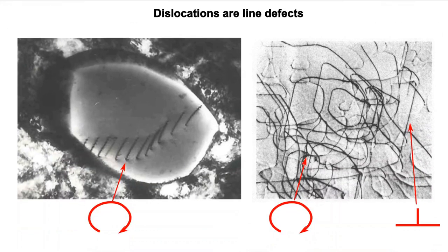These dislocations are everywhere in crystals, but are hard to see experimentally. If one has a transmission electron microscope and a thin enough section, then they can be observed directly, as shown here. On the left is some nickel showing a series of screw dislocations. On the right there is another foil which is showing a much more chaotic arrangement of mixed dislocation types, both edge and screw combining. What do these dislocations have to do specifically with the yield stress?